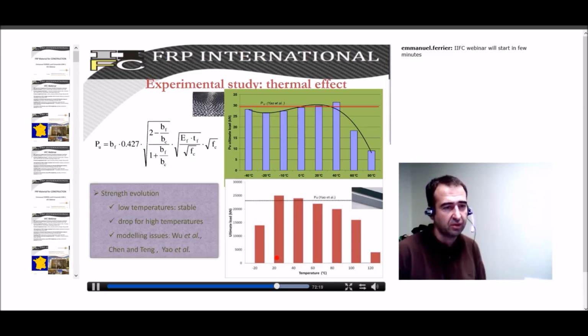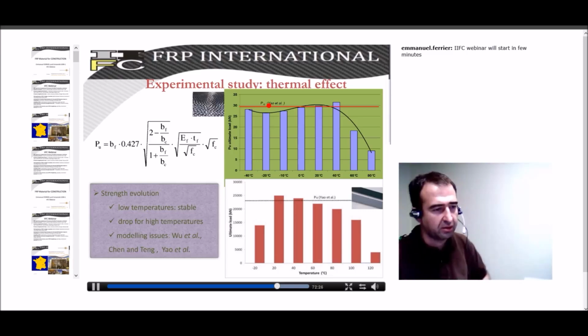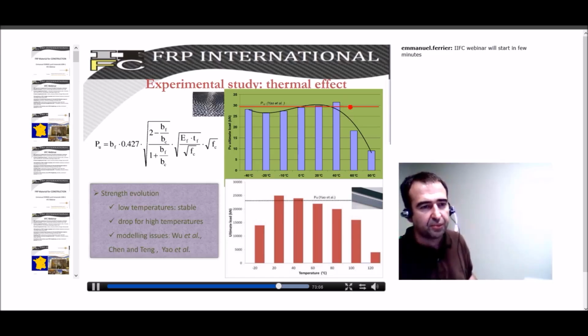In fact, if we don't do this, you can see here, for example, one model which works quite well, coming from Yao and the team of Teng. These authors published a model that works very well. And when you observe this, you can see that for low temperature, the values at failure are underestimated, which can be quite dangerous. For common temperatures ranging from 0 to 40 Celsius degrees, it's quite good. But as we increase the temperature, even at 60, which is not so high, the calculated value is very far from the results.